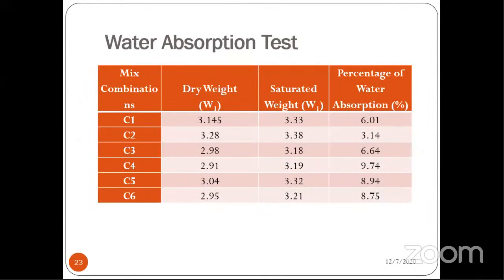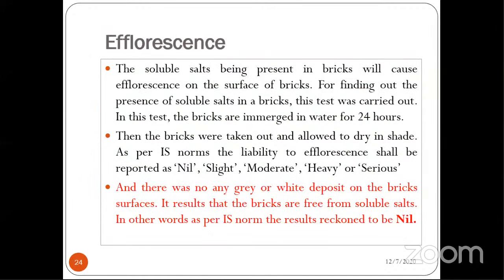And water absorption test and efflorescence. The soluble salts present in bricks will cause efflorescence on the surface of bricks. For finding out the presence of soluble salts in bricks, these tests were carried out.